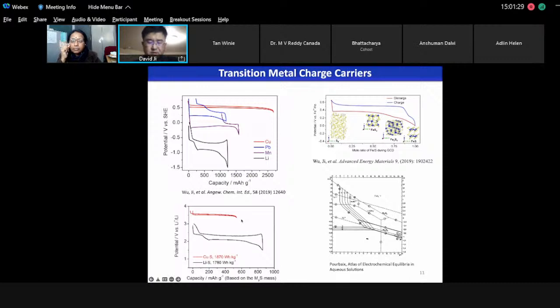So the third feature I want to highlight is we don't have the polysulfide shuttle mechanism for copper. And for lithium, it is well known, you have that. The reason is that for copper reduction and oxidation with sulfur, copper binds sulfur too strongly. It doesn't give a chance for sulfur to evolve into polysulfide. And this similar phenomenon takes place for iron, ferrous iron as well. So we don't have the polysulfide shuttle mechanism. Of course, iron battery, recently we have done several studies on iron battery with iron metal as the anode and some host as the cathode.